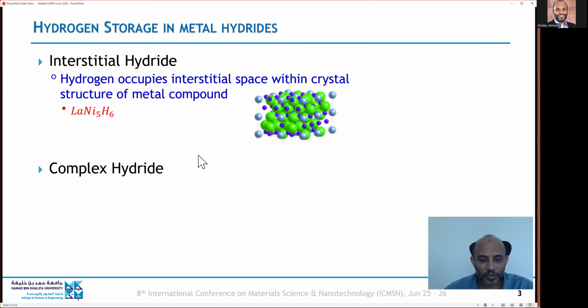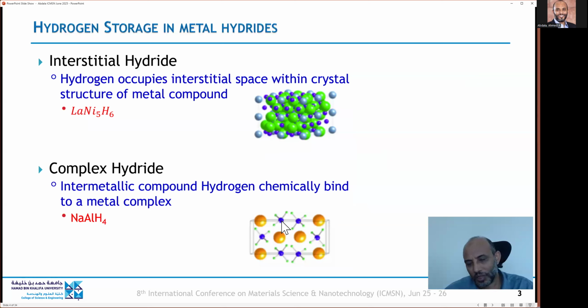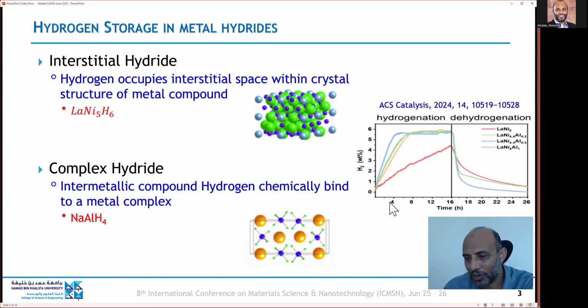The other type of metal hydride is a complex hydride. In complex hydride, we form an anion by metal coordination with hydrogen, and then this anion coordinates with a metal cation to form the complex metal hydride. An example is sodium aluminum hydride. The storage of hydrogen is two steps. The first step is the absorption of hydrogen by the metal hydride, and that's typically a relatively rapid step. So we can see here we can reach complete storage, based on the material, in about 4 or 5 hours.